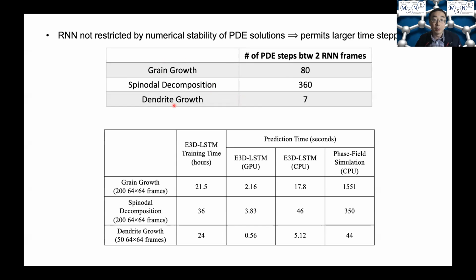So for the 3 examples we used in the testing, we can use from 7 to 360 times the time step size in the RNN prediction compared to the PDE solvers. And so combined with this time coarsening and spatial coarsening, we can achieve 100 to 1,000 fold acceleration when you run the RNN model on GPUs. And even when you run the model on CPUs, you can still achieve somewhere from 10 to several tens of fold of speed up compared to phase field simulations run on CPUs.